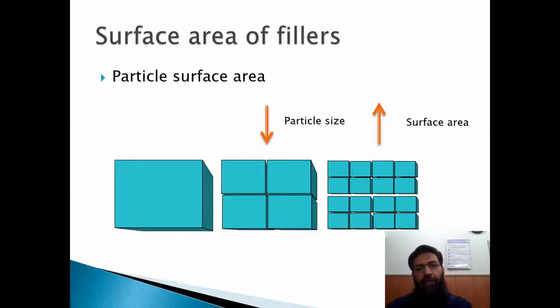Mainly, for reinforcement, we need the high surface area. And definitely for high surface area, if we reduce the particle size, we move towards the high surface area. But if by reducing the particle size we can't get the high surface area, then the surface area of the fillers can be enhanced by different surface treatment methods. For example, we can enhance the surface activity of the carbon black by putting them in the furnace or in the oven at the high temperature.